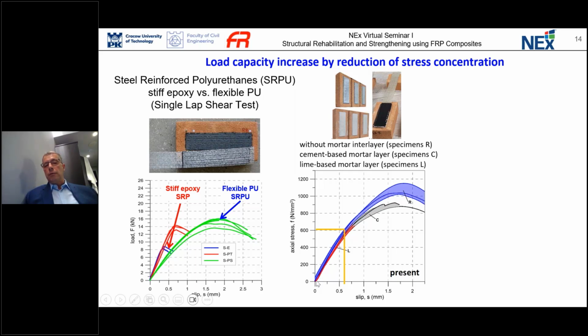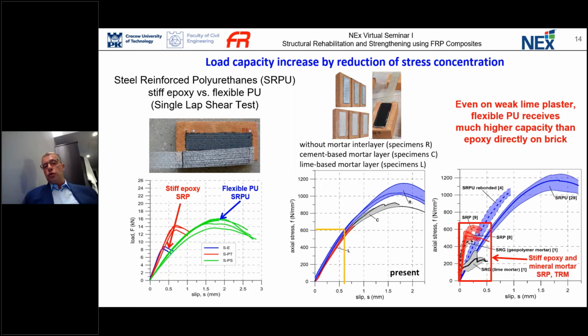So you can clearly see that the behavior of this system is very similar to the behavior of this flexible bonding material. If we compare in literature in the same scale the effectiveness of this system bonded on the plaster with flexible bonding, you clearly see that it is more effective than lime mortar strengthening with composite materials, the same steel fibers as a matrix. Also, when we use geopolymer or polyurethane epoxy resin, polymer epoxy resin, in this case, all these systems are weaker than in the case of steel reinforced polyurethanes when we use flexible polyurethane matrix.